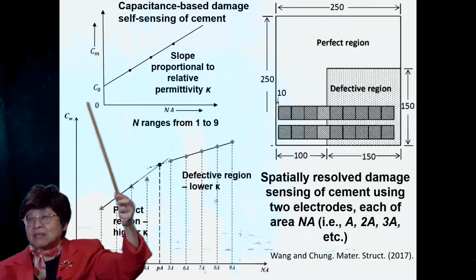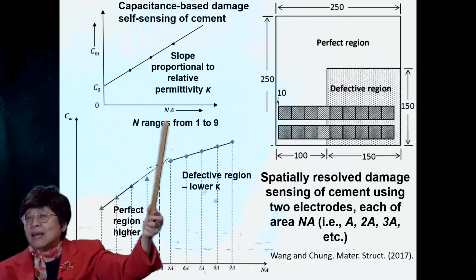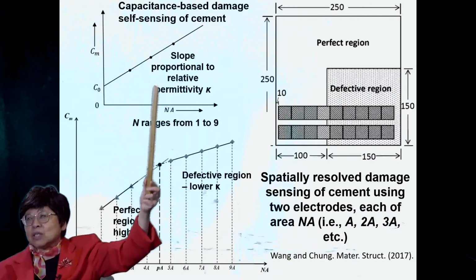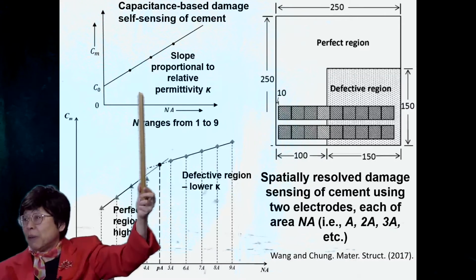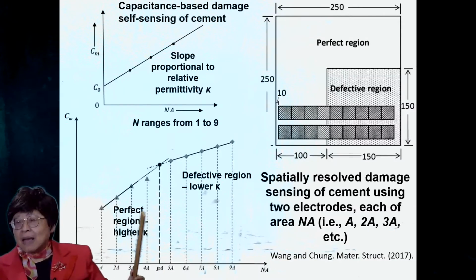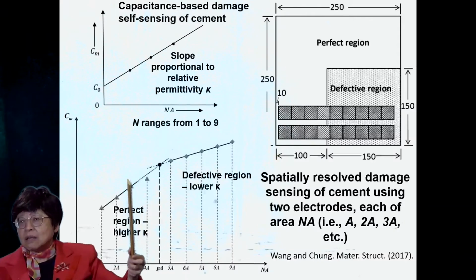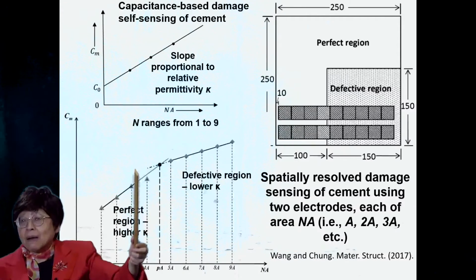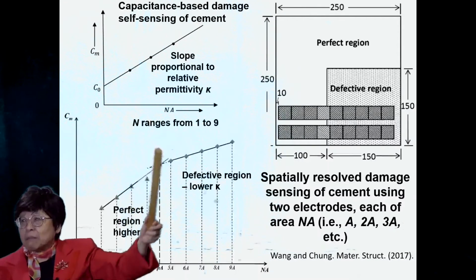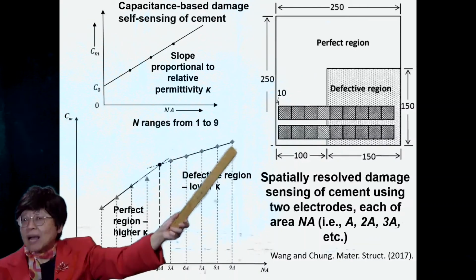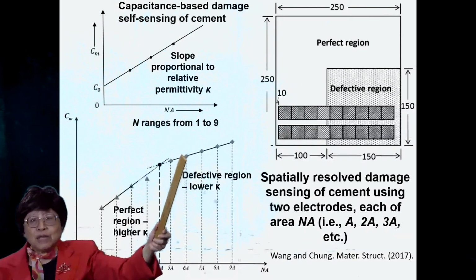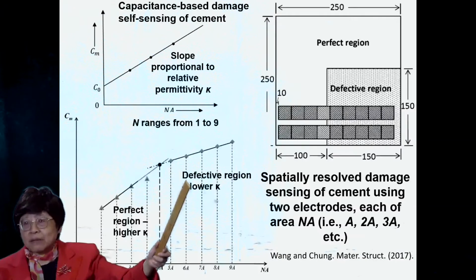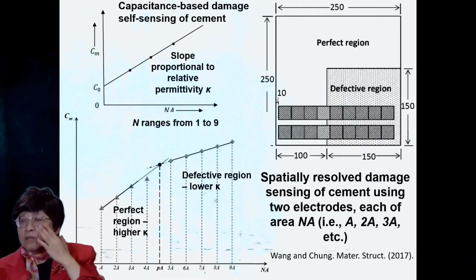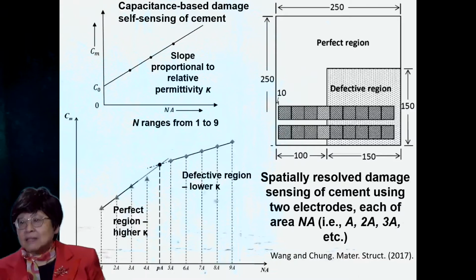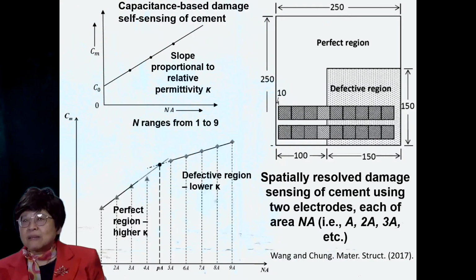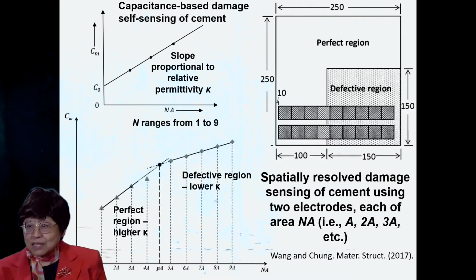And so this is the capacitance versus N of the NA. And the slope relates to the permittivity. And we see that the slope changes. It's a bigger slope for the perfect region and a shallower slope for the defective region, because the permittivity is smaller in the defective region. So we have spatially resolved damage sensing of the cement using capacitance-based self-sensing.